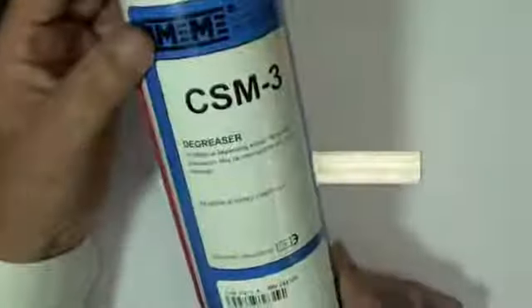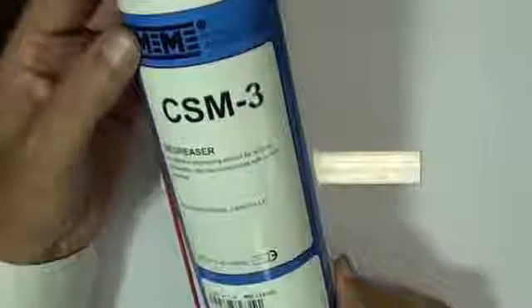To do this, he's going to use the Micro Measurements product CSM3. This is a very powerful degreaser, and it's applied by spraying it into a gauze pad. If you spray it on the beam, it's going to evaporate very quickly and won't be as effective. If you spray it into the gauze pad, it's going to stay liquid for a longer time and allow you to work with it. You can see Vijay is degreasing the entire beam, not just the location where the strain gauge is going to be bonded, because we don't want the possibility of dragging contaminants back into the gauge location. And you can see by the look of the gauze pad that he's showing, we actually did remove some material. This is a very important step.